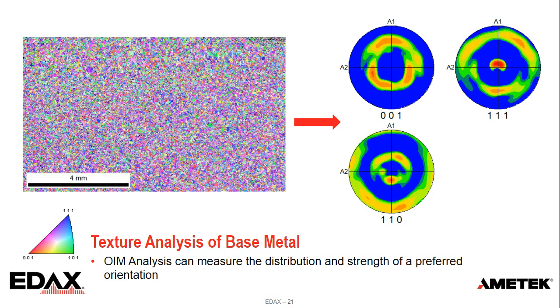What this shows us, if we look at the 111 pole figure, is there's a strong peak in the center of the 111. It's a little bit offset, kind of coming out of the center of the sample. That's why when we look at that region, there's a good amount of blue. If we had the scale bar, we'd be able to tell how much over random that distribution is. And we can see it's sort of annular around that. It's what we'd generally call a fiber texture, or at least close to a fiber texture. It's got some funny shapes to it, but we can see it's more randomly distributed around the clock face of that 111. So that's what texture can show us.